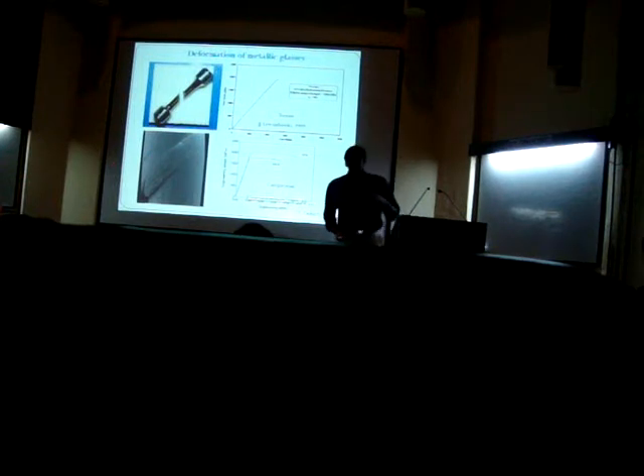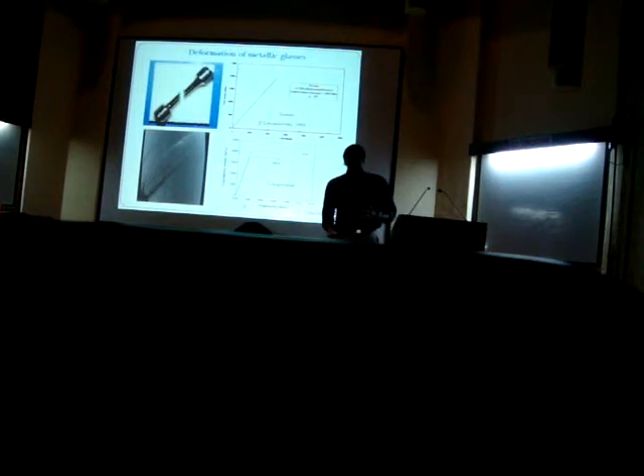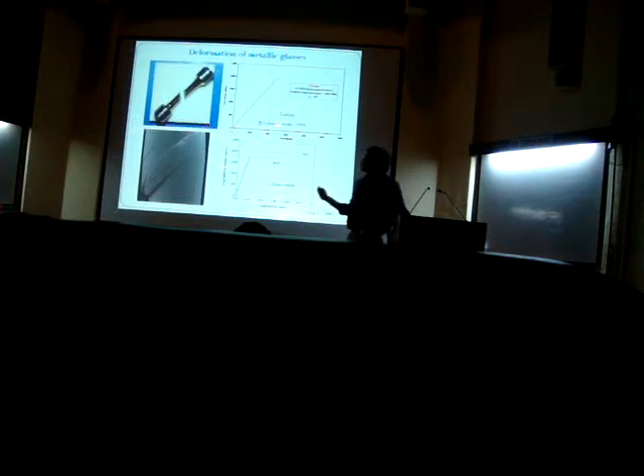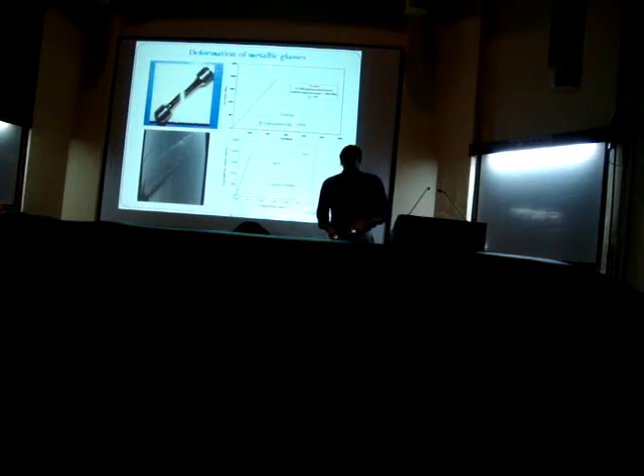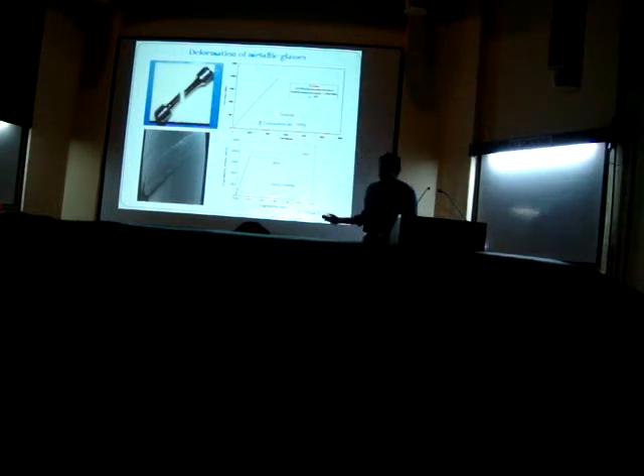But these lines are shear bands, which can propagate in tension unhindered, since there is no microstructure to prevent the shear bands from going off. And in tension, this results in catastrophic failure. That is, you don't have any extension after it yields. But in compression, there is no such instability, which is why your specimen can actually deform pretty decently, and you can have formation of multiple shear bands, and you have some form of strain to failure, plastic strain to failure.